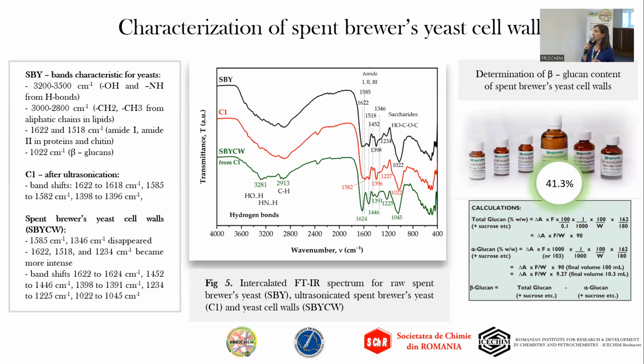Spent brewer's yeast cell walls were characterized by means of Fourier transform spectroscopy and beta-glucan content. The spectra of raw biomass of spent brewer's yeast, of the optimal sample, and that of yeast cell walls obtained from the optimal sample were assessed. The spectrum of the raw biomass presents mostly bands characteristic for yeasts, for example, for hydroxyl and NH from hydrogen bonds, for methyl groups that are present in lipids, for amide 1 and amide 2, that are groups present in proteins and chitin, and also bands that correspond to polysaccharides, mainly beta-glucans. These are, of course, the main components of this biomass.